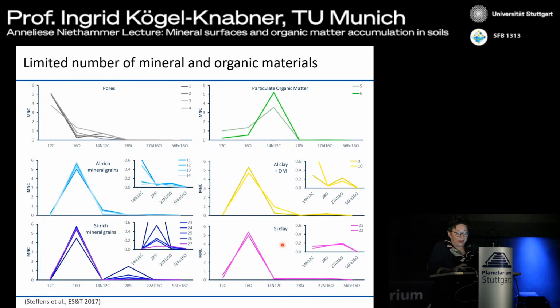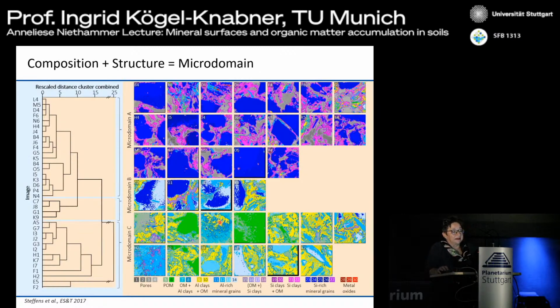And if we try to combine all this, what we get is these patterns. What was new for us and what I think is interesting to see is that in this one aggregate, we have two types of microdomains. Pores and mineral grains and clay minerals are not randomly distributed, but we find these structures here, and we find these structures here, what we call microdomain C and microdomain A, and B is where they meet, basically. So what you see is that these materials here have a lot of large gray parts, so they are, I can't let that go by, pretty porous.